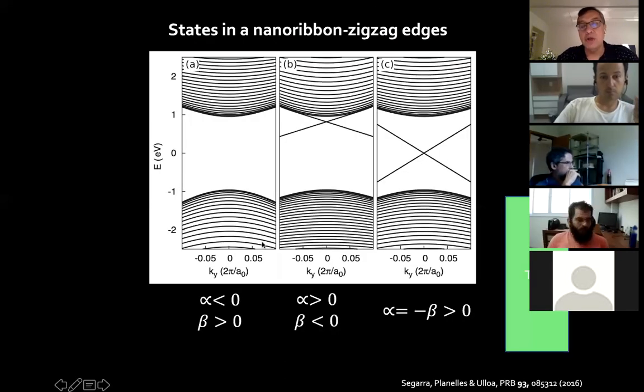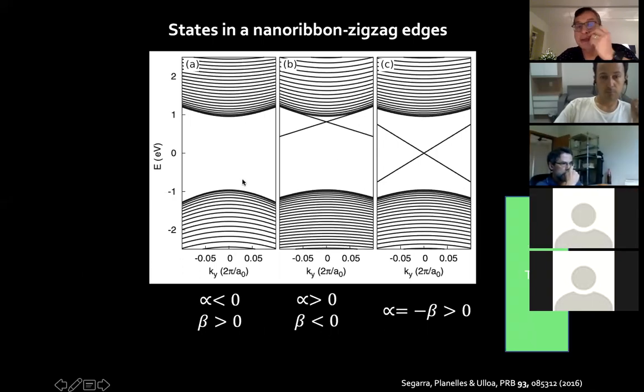You put a Hamiltonian on a grid and you can play around with the various values of alpha and beta. In the regime where alpha is less than zero and beta positive, you have a clean gap, which is just a trivial semiconductor. But for different values, with alpha positive, all of a sudden you have edge states that appear. This is the K valley, the K point. Depending on the values, of course, these states can move around in the gap.